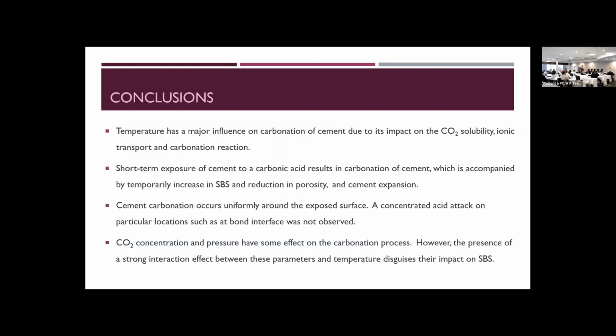To conclude, we have seen here that two major elements are having a major influence on the bonding, and we also notice that the temperature has a major influence on carbonation of cement due to its impact on the CO2 solubility, ionic transport, and carbonation reaction. Short-term exposure of the cement to carbonic acid results in carbonation of cement, which is accompanied by a temporary increase of SBS, so shear bonding strength, and reduction in porosity and cement expansion. Nevertheless, CO2 concentration and pressure have some effect on the carbonation process. However, the presence of a strong interaction effect between these parameters and temperature disguises their impact on shear bonding strength.